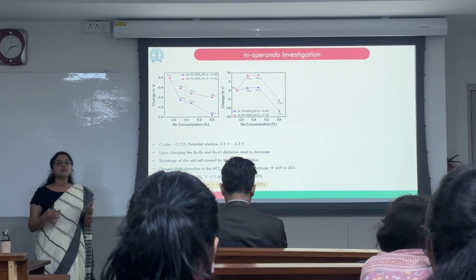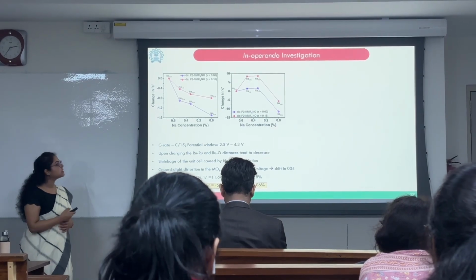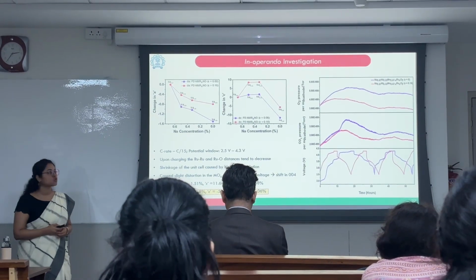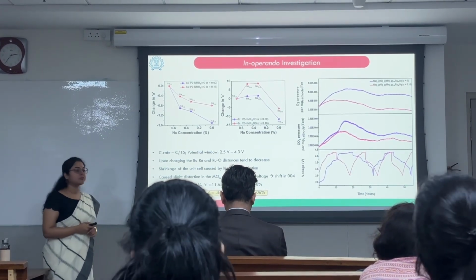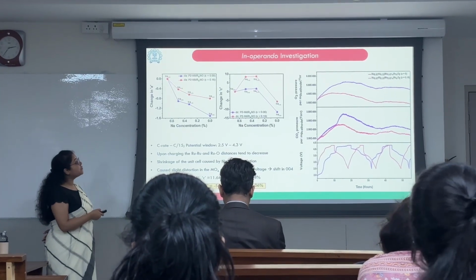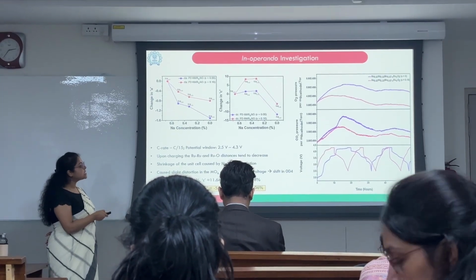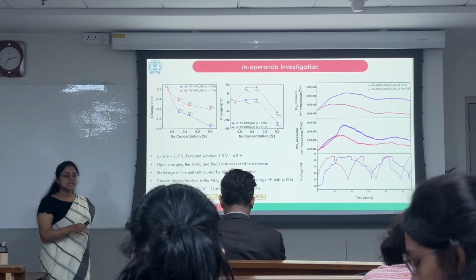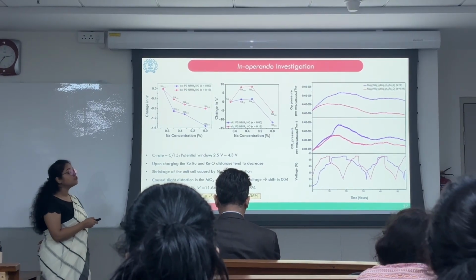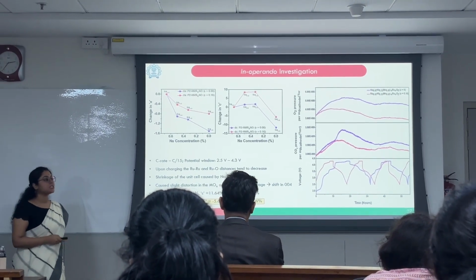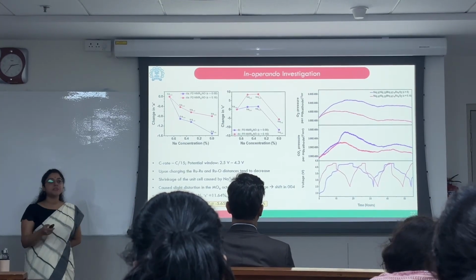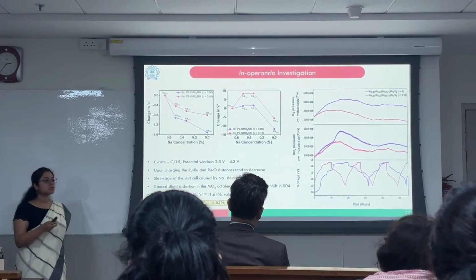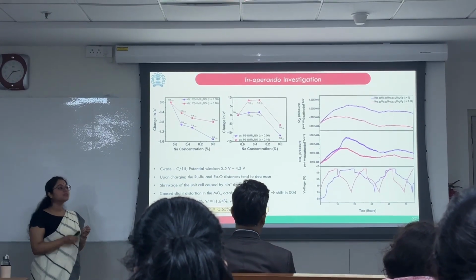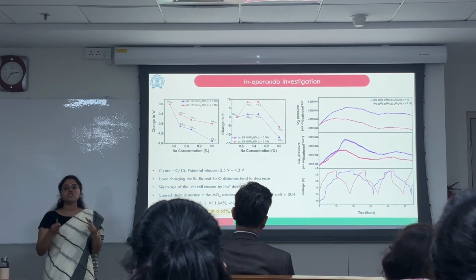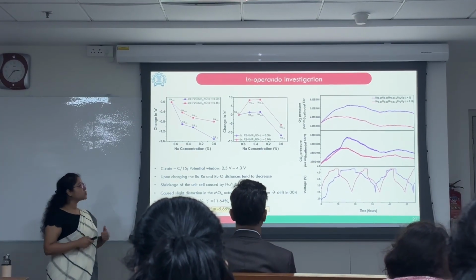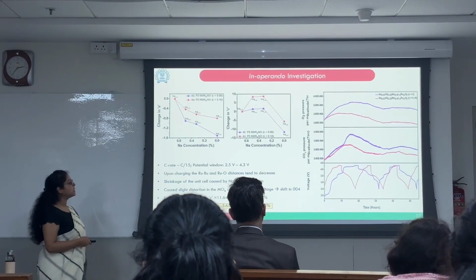Since we are looking at the oxygen loss, we conducted online electrochemical mass spectrometry at a slower rate of C/15, and we observed that the CO2 gas and the oxygen gas evolution have been significantly suppressed, which suggests that definitely ruthenium is able to stabilize the structure with the help of the ligand to metal charge transfer mechanism. That is why the ruthenium is holding the structure.